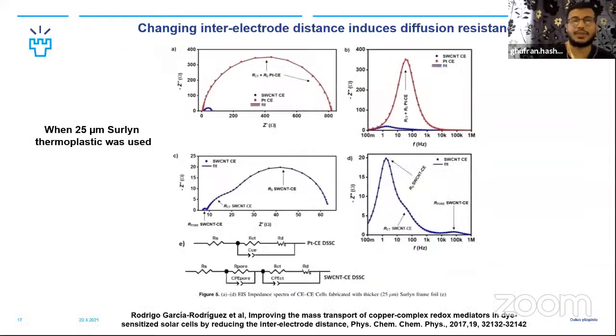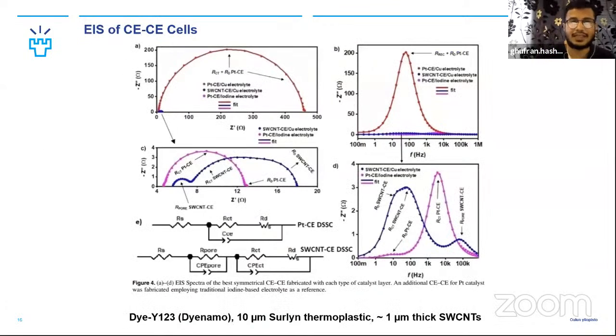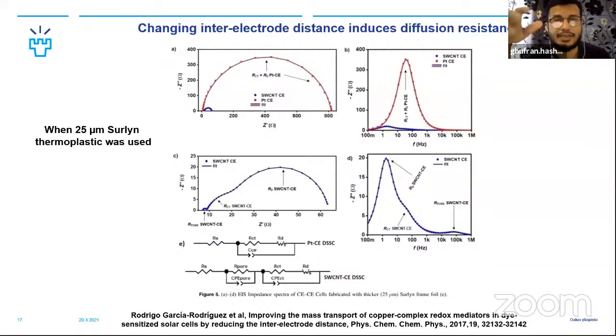Another fact is that, because of this bulky redox couple, they exhibit very high diffusion resistance, as you can see here. In these results, we fabricated devices with a 10 micrometer Surlyn thermoplastic. However, when we made the symmetrical cell with a 25 micrometer Surlyn thermoplastic, you can see a significant increase in the diffusion resistance. That gives you an idea of how you should optimize the device structure in order to extract the best performance of your devices.